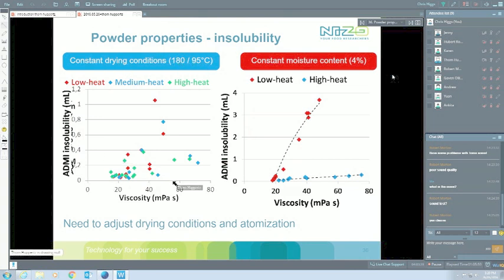Basically different solids contents from low heat, medium heat, high heat powders. And they have different starting viscosities, of course. And we put them on the dryer. 180 inlet, 95 outlet. And we see that our more viscous concentrates start getting a lot more insolubility. Same way, of course, when we dry to the same moisture content. So we dry them all to 4%. And what we see is in the high heat samples, it's not too bad.